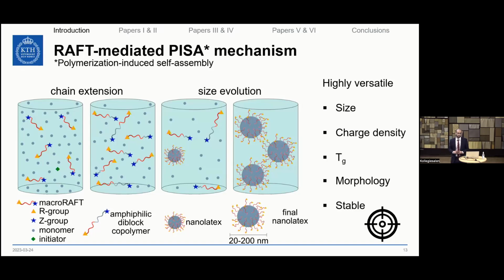This RAFT-mediated PISA technique is highly versatile because you can target the charge density and size of the nanolatexes that you prepare. You can play around with the glass transition temperature of the core and the shell components that you used. You can have different morphologies. You can have spheres, worms, or vesicles. And the final nanolatex dispersions are quite stable.